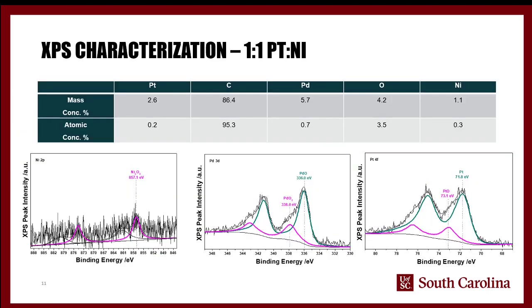And along the same lines, you can use XPS to do a characterization as well. XPS is a little bit weaker because we're using nanoparticles, and so, for instance, you can't really see that the nickel is there. You can kind of pick it out from the background, but it's not a very strong signal. But we can still extract mass and atomic concentrations. And the big thing that we see here is that the atomic concentration of the platinum and the nickel are roughly in the same ballpark.